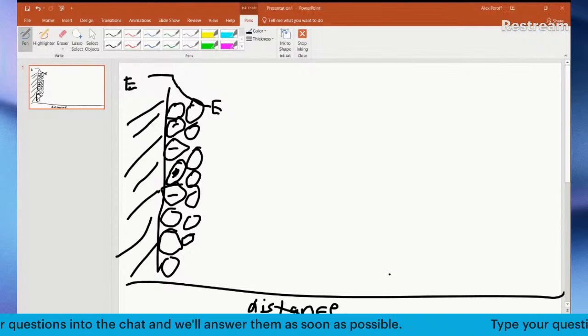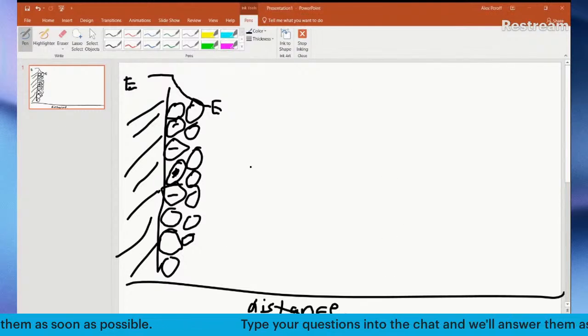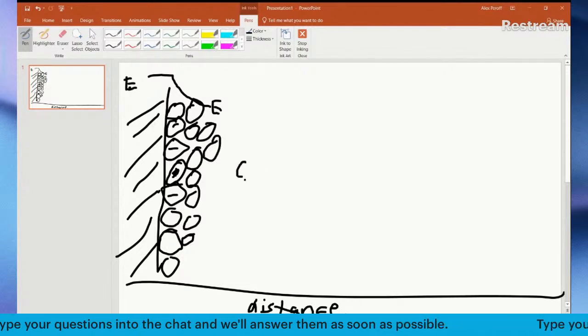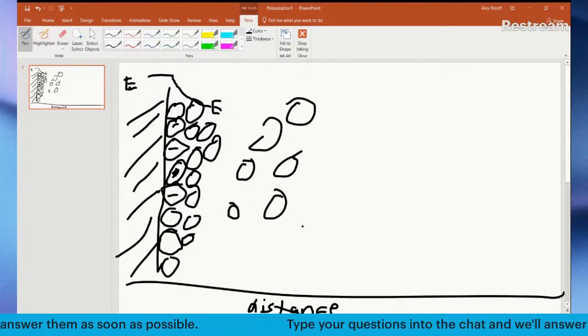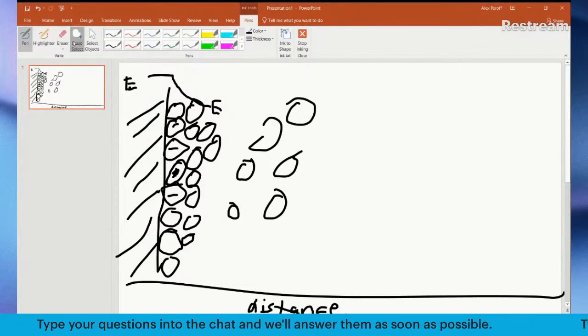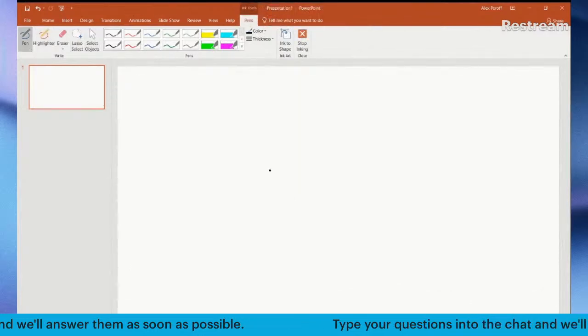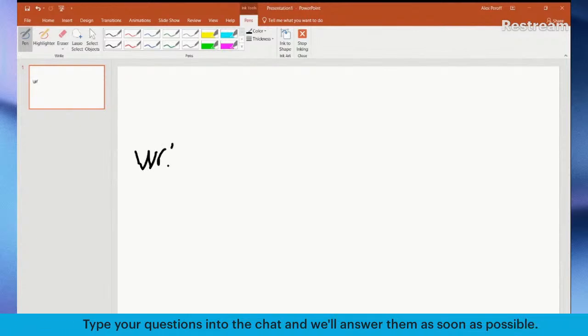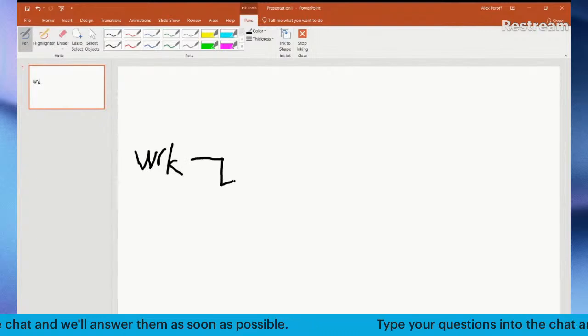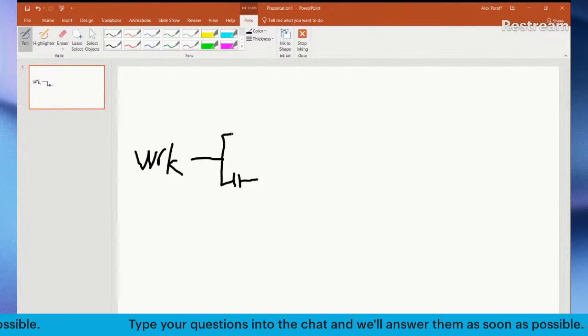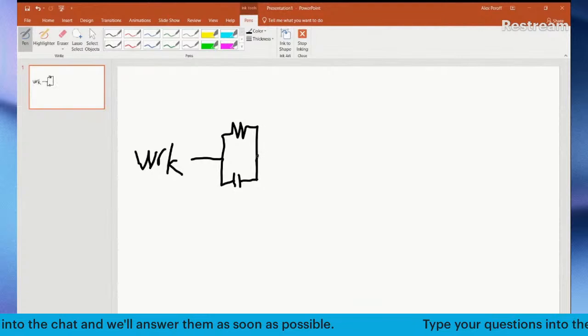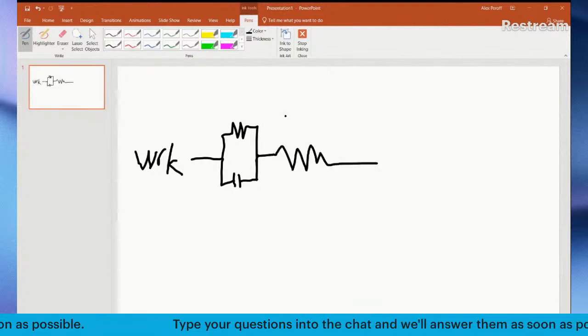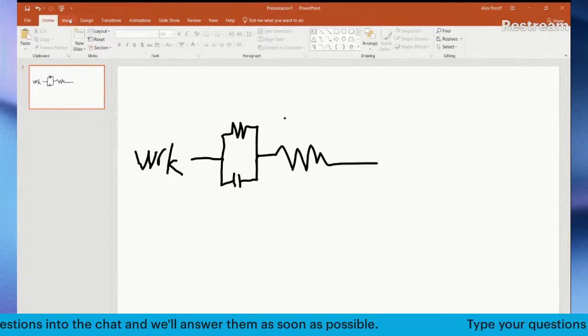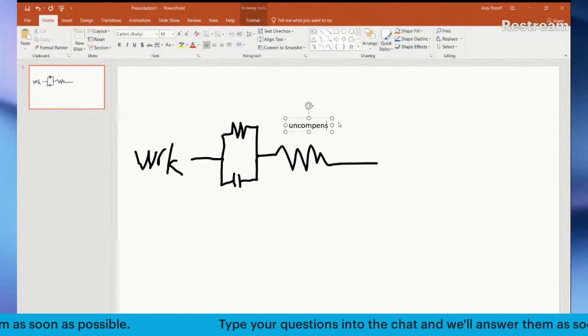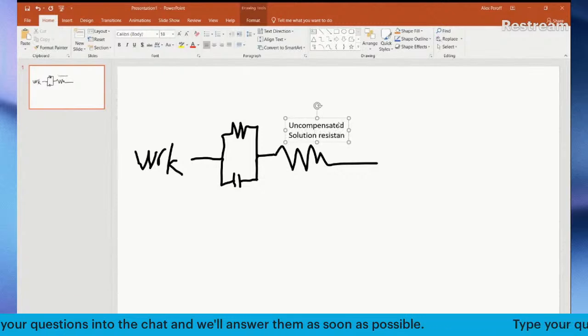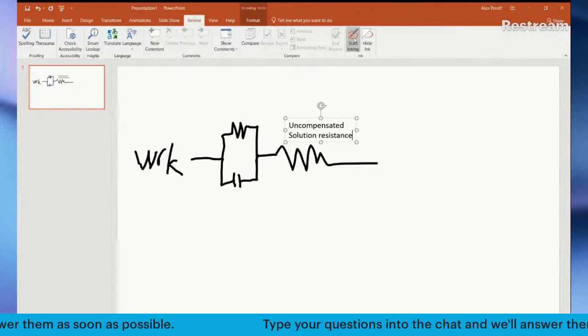Now the other type of potential drop has to do with solution resistance. So it's this bulk resistance in the solution. And it's easiest to think about this using a circuit diagram. Okay, so let me delete this and show you. If you have your working electrode, which is your conductive metal, and then you have your electrical double layer capacitance. You have charge transfer resistance. And then you have what's known as bulk solution resistance, which is what's known as uncompensated solution resistance.